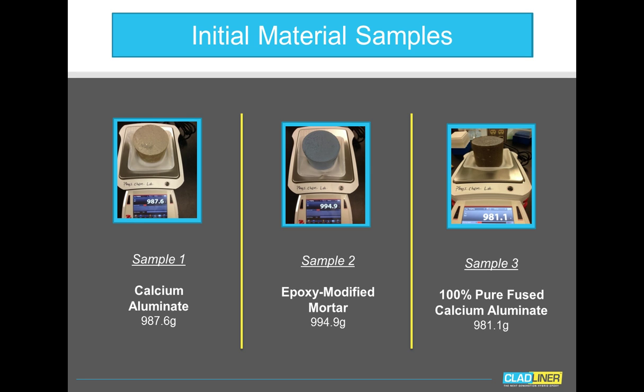So let's look at some of the initial material samples. The first one is the calcium aluminate. The core sample here is still obviously intact. It's brand new. All of them were allowed to cure according to the data sheets beyond where they could be returned to service in a normal working environment. The calcium aluminate was about 987 grams. The epoxy modified mortar, as you can see by the blue color, that's one of the differentiations, was 994 grams. And the 100% pure fused calcium aluminate was 981 grams. So they're all within 1% of each other's weights at the start.